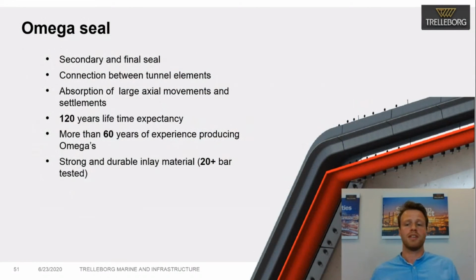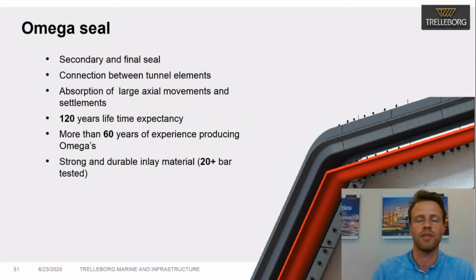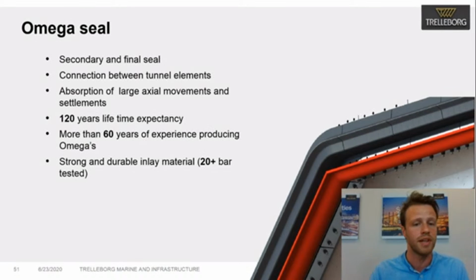So the omega seal, as I mentioned, is a secondary seal. It's not being loaded due to compression, but it functions as a membrane basically to cover up the joint. We also have 60-year-old samples of these types of omega seals due to renovation works in Rotterdam. That gave us a lot of information on how that particular seal was performing over the years. And we tested the seal for more than 20 bar of force.